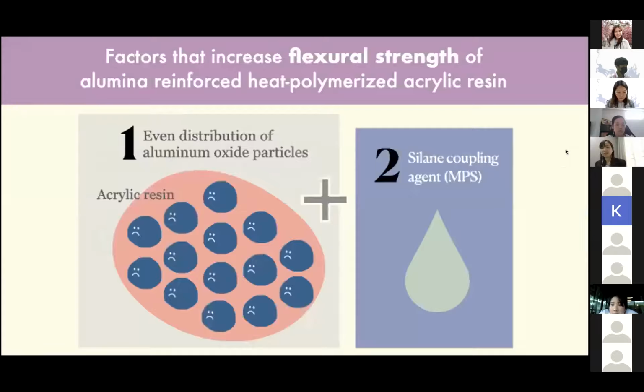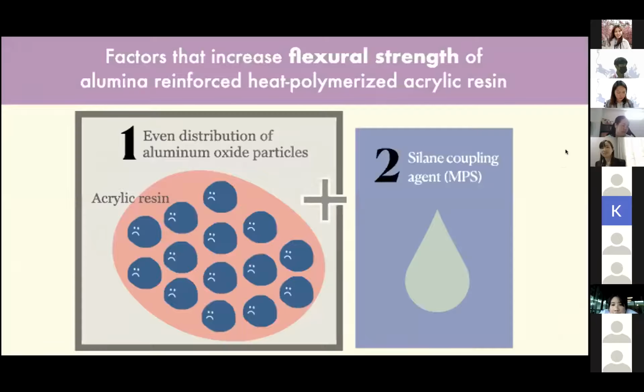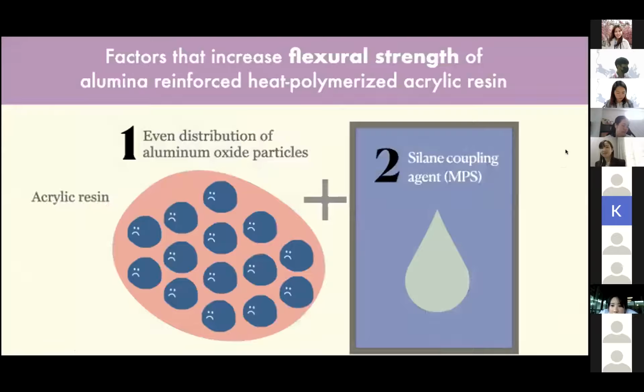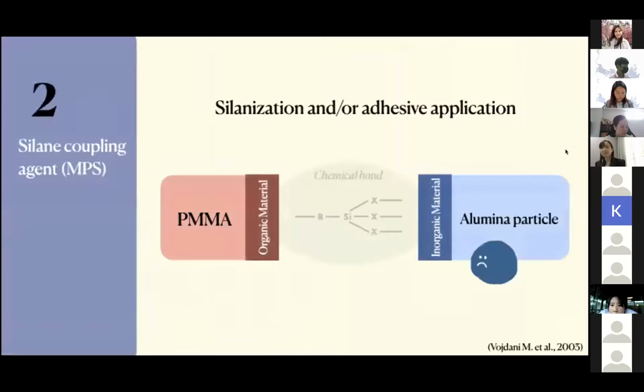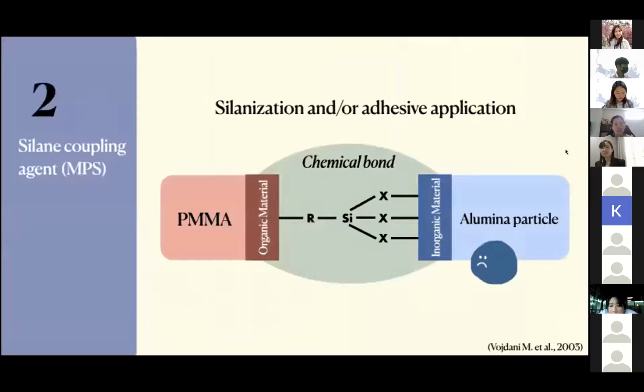Two factors improve flexural strength of alumina reinforced heat-polymerized acrylic resin. First is the even distribution of the aluminum oxide particles. Second is the treatment of silane coupling agent on the reinforced particles. Coating the particle with silane helps to form a chemical bond between PMMA and aluminum oxide.